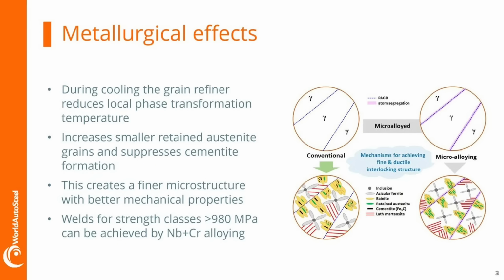During cooling, the grain refining elements in our microalloyed wire will segregate at the phase boundaries and reduce the local phase transformation temperature. This will increase the formation of smaller retained austenite grains and in turn also suppress carbon reactions of the steel, so less cementite is formed. And this creates an overall finer microstructure, which has better mechanical properties per definition.